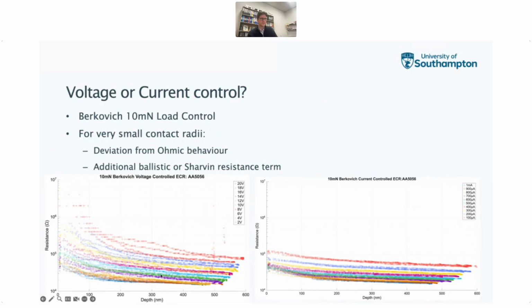So the bottom voltages here are the 20-volt region down here, all the way up to the 2-volt region. Or with the current control, where we've set up to 20 volts, and we've gone from a milliamp down here, all the way up to 100 microamps at the lower end. Now you notice that where the depth is higher on the right-hand side of these graphs, we're getting a very linear response, and that's because the contact is in the ohmic region.